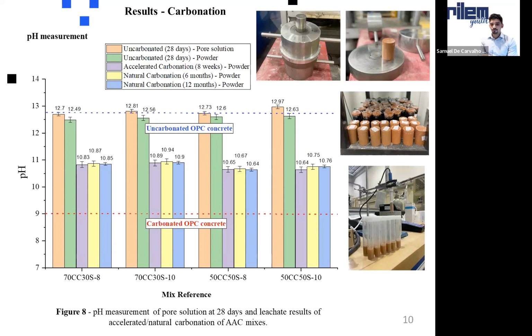So you did it for the uncarbonated samples at 28 days. All the materials were sealed. The four mix designs I showed you before all showed a really high pH after 28 days, around something above 12.5, which is very close to the OPC concrete pH, very alkaline. So you used two different methods for this 28 days. You used the pore solution extraction, and you also used the powder